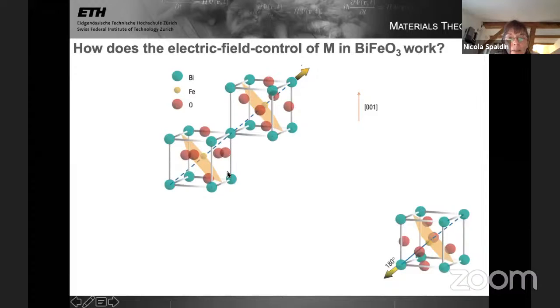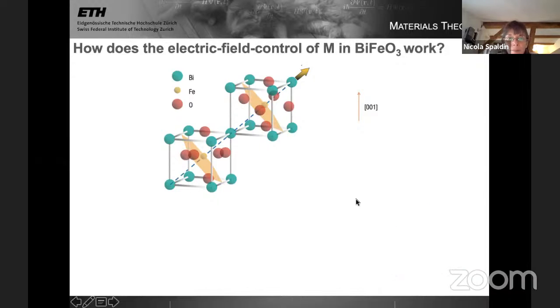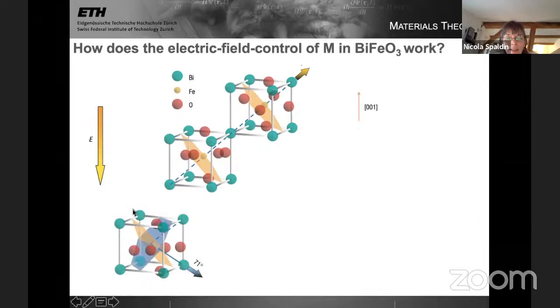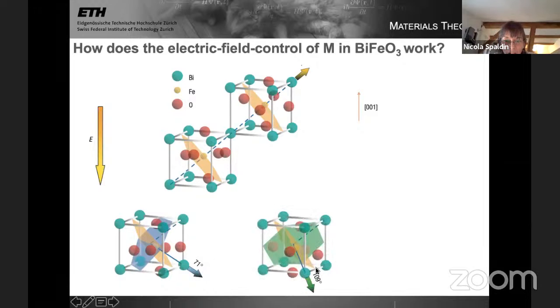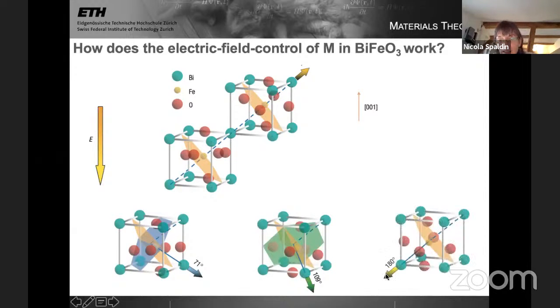But this is a thin film, and the orientation of the film is such that the bottom is the bottom of the page, and it's grown in this 001 direction. So when I apply an electric field, it's applied just in the down direction. The polarization starts off net in the up direction. I apply an electric field in the down direction. And what happens is that the polarization doesn't go straight through to the other side. The structure gets distorted, so the polarization switches from one corner of the unit cell to the next one, goes by 71 degrees, and then another corner around again, and eventually makes it to the other side. So the elastic deformation associated with the electric polarization moves around as the polarization goes from one corner to the other and out to the other side.